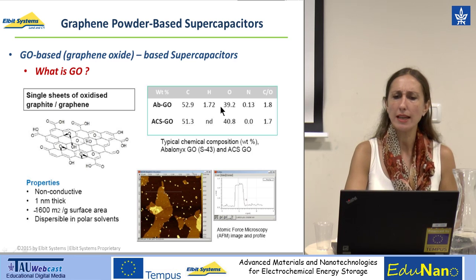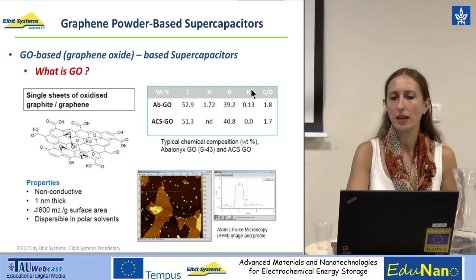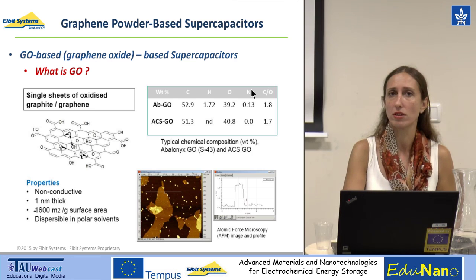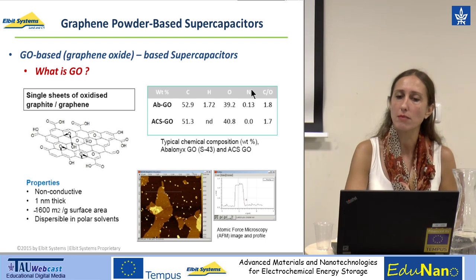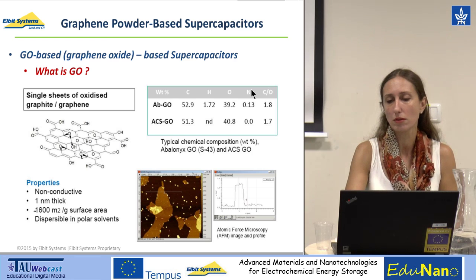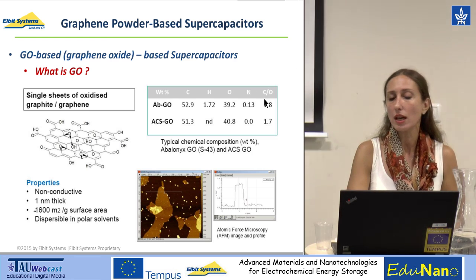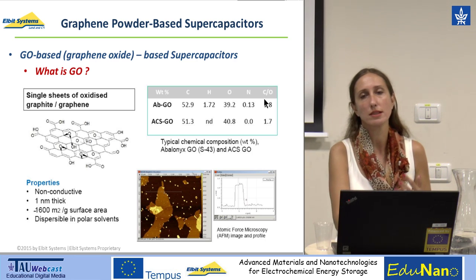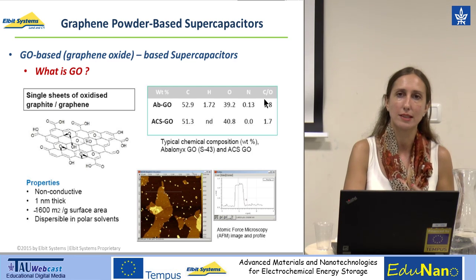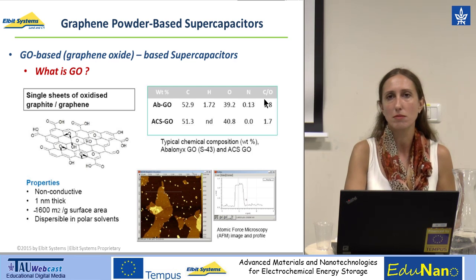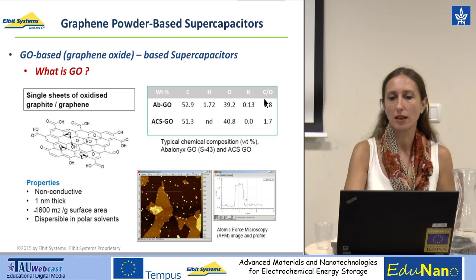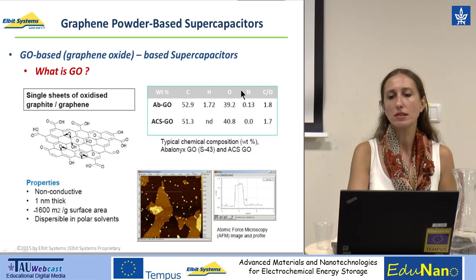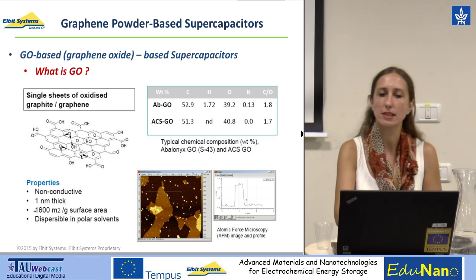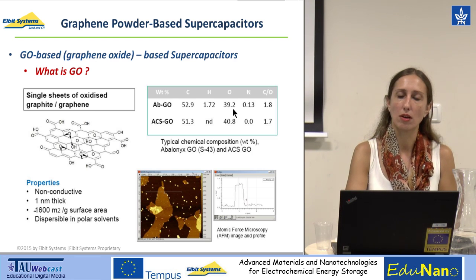The ACS GO product has a lower carbon content as well as a higher oxygen content, so we are talking about more or less the same carbon to oxygen ratio of 1.7 in comparison to 1.8. The hydrogen content is so low that it cannot be detected via conventional detection methods such as SIMS or absorption methods. And also, what we have in this material is mainly pure carbon and oxygen.